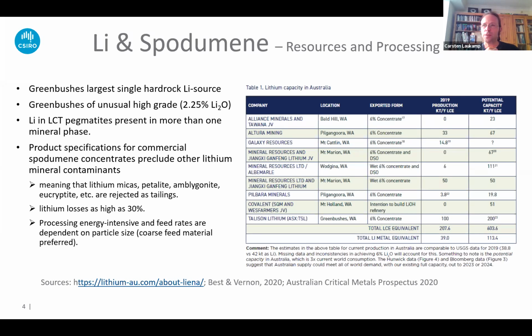The processing of lithium is also quite energy intensive, especially if you don't have just the nice coarse-grained spodumene. And the feed rates are dependent on the particle size, so grain size is an important aspect as well. So it's not easily said that we've got enough lithium, or like Elon Musk said, that there's enough lithium in the seawater. Well, it's good, but you can't really get to it easily.